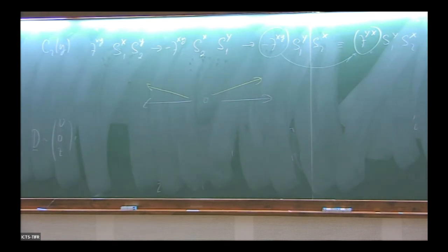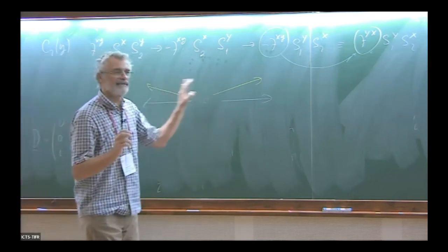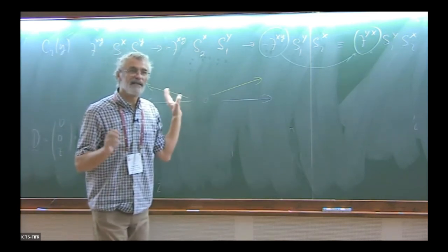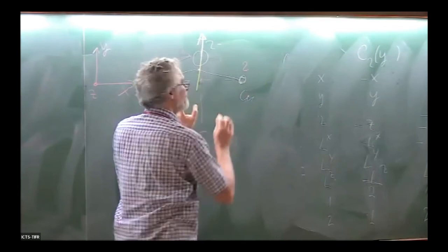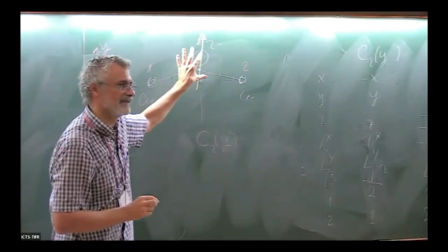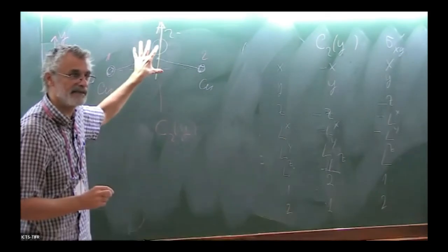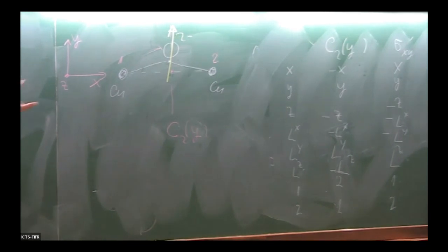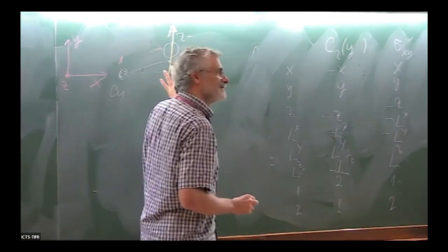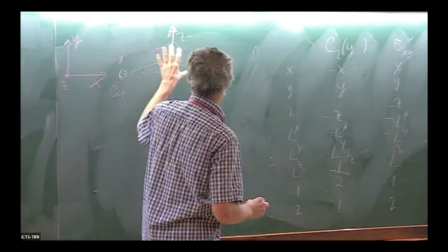We can think also differently. Suppose that we have some spin configuration where the spins are not parallel to each other, but have some angle. If this is so, it is possible, and this really happens, that non-collinear spins will give rise to an electric dipole moment. This is the so-called magnetoelectric coupling, and it is made possible because of spin-orbit interaction. This is the Katsura-Balatsky-Nagaosa mechanism, I think.